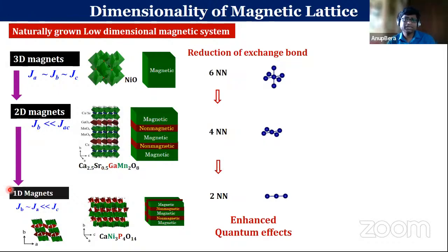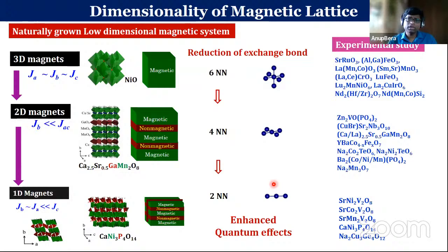So what happens really when we go down to lower dimension? Basically, we are reducing the number of exchange bonds. In 3 dimensions, there are 6 nearest neighbors. For 2 dimensions, that goes down to 4, and 1 dimension goes down to 2. And we have been working on different magnetic materials, mostly based on oxides, to study their interesting properties. They belong to these kinds of dimensionality.